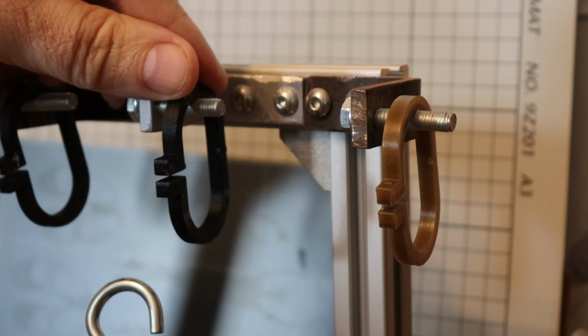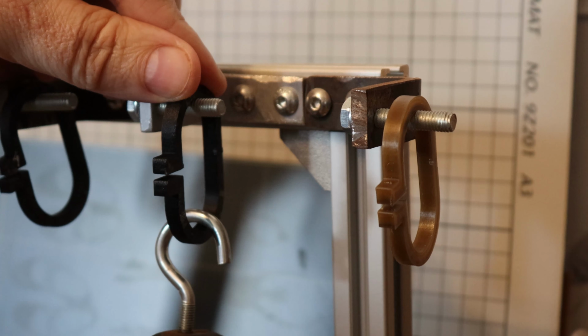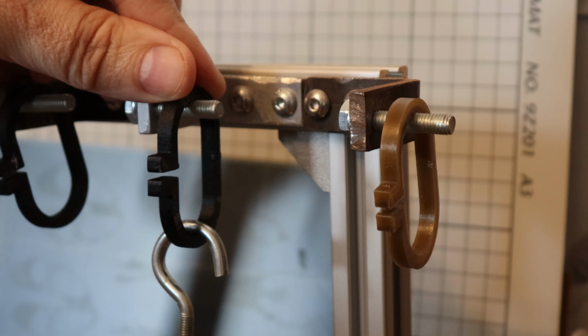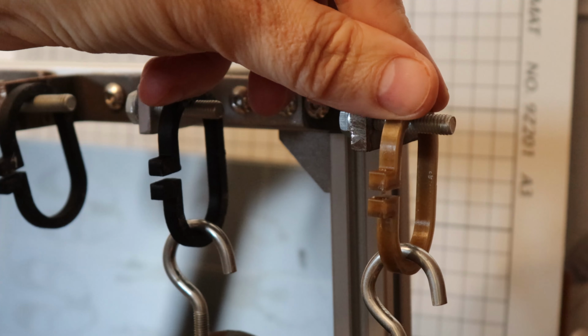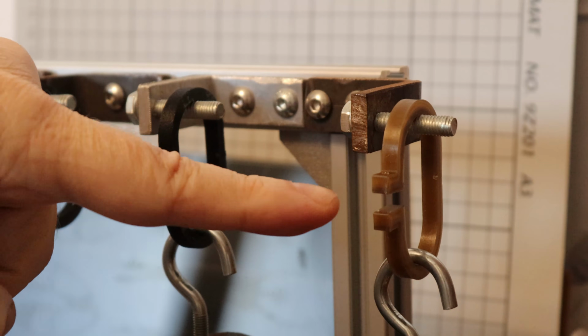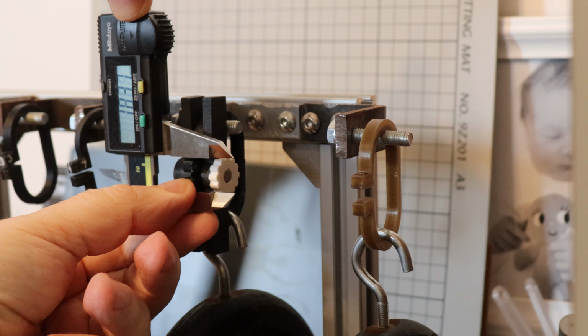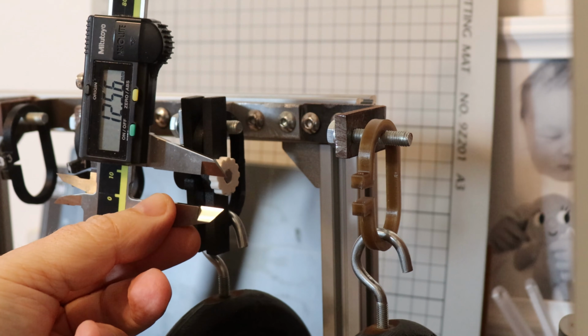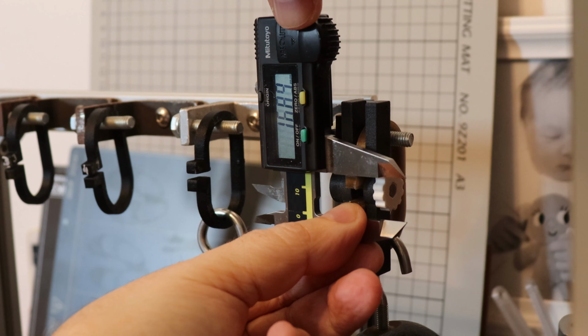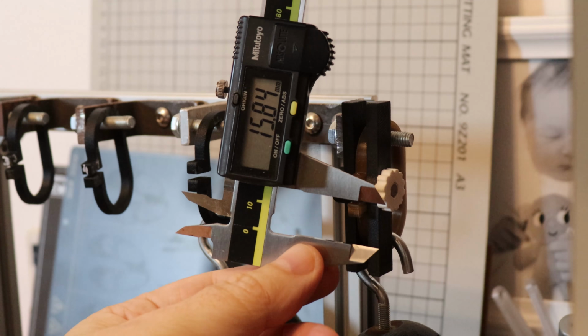The creep tests: the deformation under the constant load of 1.25 kilograms. Oh, much bigger deformation. 12.56. 15.84. I always start the testing with the creep test because it's the longest, so that's why I was surprised here. And I measured them every day, and let's see the last 5th day.